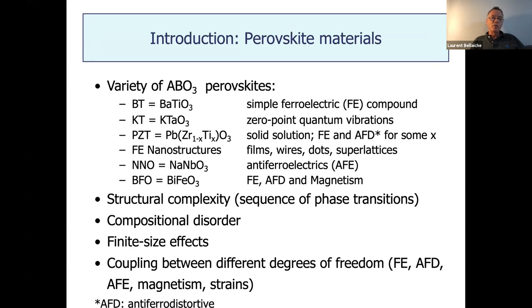So quite a complex system, with a lot of different phase transitions. For example, in sodium niobate, you have 7 phases as you decrease temperature. You can have compositional disorder in alloys. You can have finite size effects in these nanostructures, and you can have coupling between different degrees of freedom: ferroelectric, strain, tiltings, antiferroelectric, magnetism, etc., in these systems. So easy formula, but not easy physics.